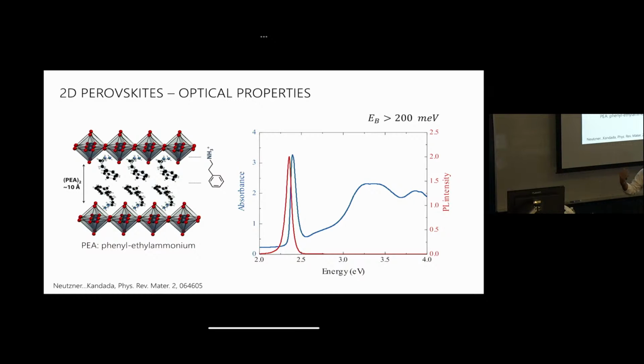Lattice vibrations are going to play a very important role in the optical properties, as well as electronic properties, thermal transport, and so on. To what extent is this highly dynamic, noisy environment important in defining the nature of the fundamental quasi-particles that give rise to the optical properties? That's a very important issue, because I'm going to show you that charges, photocarriers, are polaronic, as Esteban has nicely shown us. They're very strongly dressed by the lattice, in a regime very different from gallium arsenide, and very different from very soft materials like organic semiconductors. We're in some intermediate regime that is very difficult to describe quantitatively.